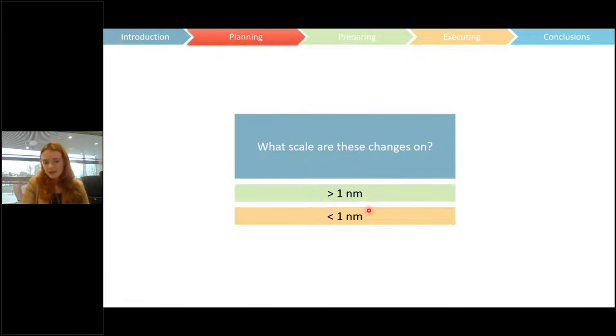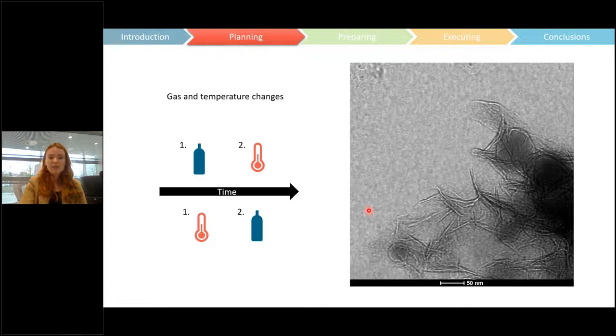So the next question to answer is, what scale are these changes on? Neither of the answers here are actually wrong, but it is much easier if your changes are bigger. And the reason for that is drift. So Minka already said that with temperature you see a quite significant drift. I think it's about one nanometer in the Z direction per degree, or might be two, I can't quite remember. But you see quite a significant Z drift as you change temperature. But the other thing that happens is when you introduce the gas, the windows bulge and your sample shifts. So as you change gases, you also shift your sample quite significantly. And that is actually much harder to follow.